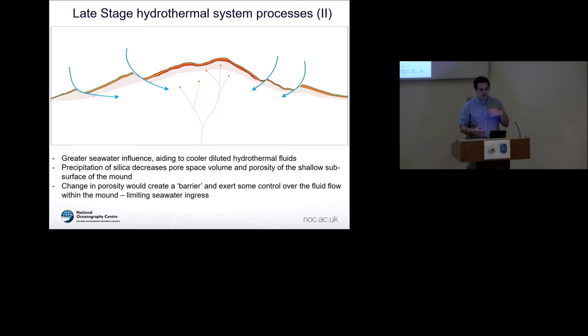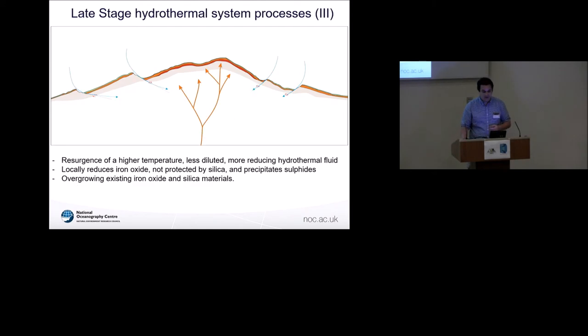And you're likely having a change in cyclicity. You've got iron oxide precipitation, silica precipitation, iron oxide precipitation, and this is probably quite varied across the whole mound itself. And then the final piece of evidence we have here is this real late stage process of potentially a resurgence of high temperature fluid. We're basically getting a scenario where there's iron oxide material that's either less coated in silica or less protected, that's then available to be reduced, available to be remobilized and reprecipitated as actually iron sulfides. And that is quite a curious feature where we have that juxtaposition of oxidized material and reduced material in the same environment. So ultimately, these processes are theoretically ongoing at the end of this deposit type.